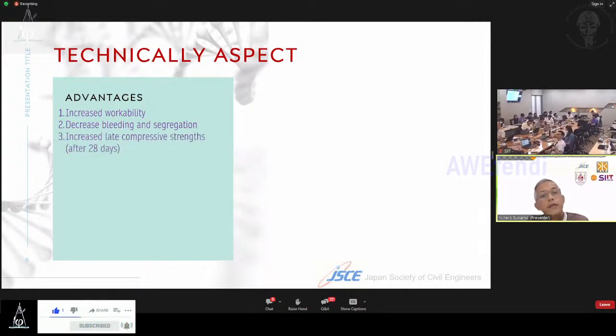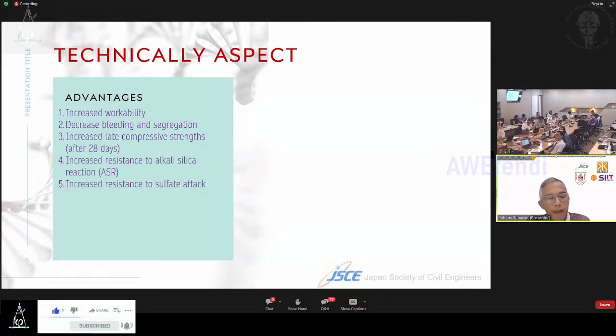The third, increased late compressive strength. Fly ash causes low initial compressive strength in concrete up to 28 days. But after 28 days, the increase in compressive strength continues until more than 120 days. The fourth, increased resistance to alkali silica reaction. Five, increased resistance to sulfate attack.